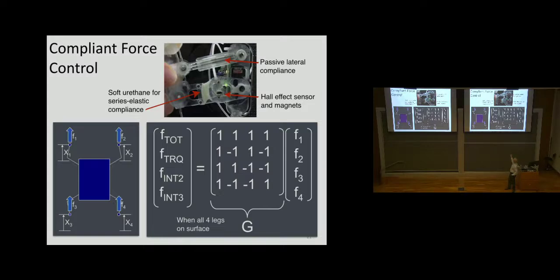And the way we monitored it is, so this is another soft robotics thing. The clear plastic here is a hard urethane, tough, but kind of like a polycarbonate. And then this cream-colored material is quite soft. It's giving us some compliance to the limbs. But that also gives us a way of measuring force, because we've got a little Hall effect sensor and magnet set up here, so that as that creamy urethane deflects, we're measuring that deflection, which gives us an estimate of the force at these limbs, so that we can do our force balance.